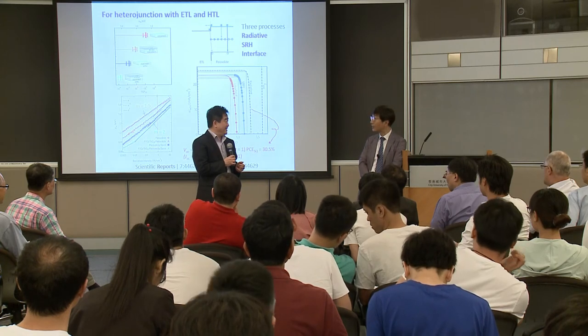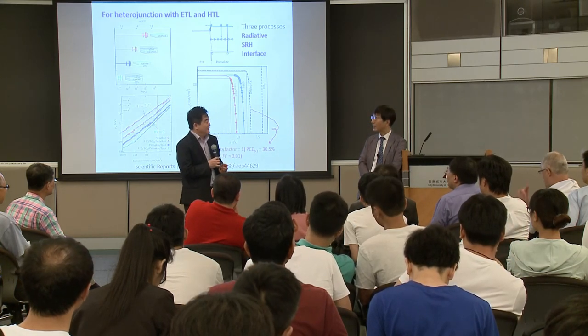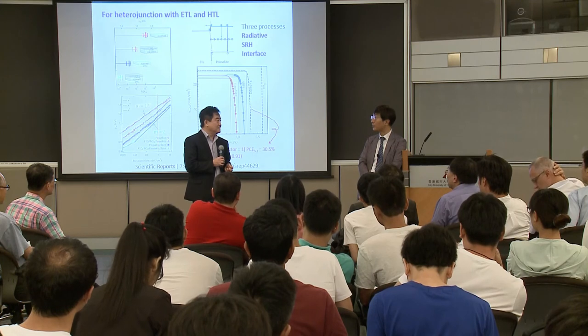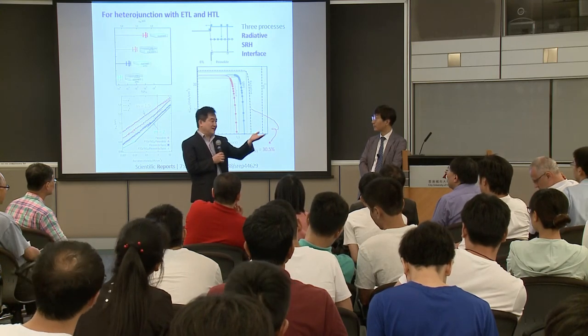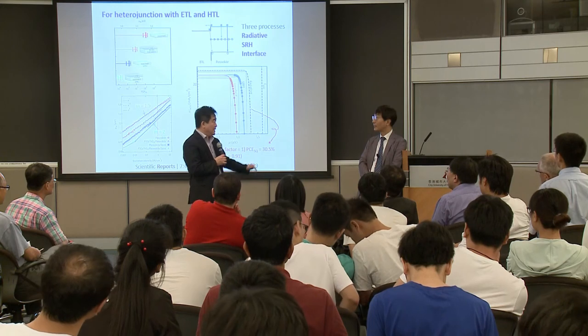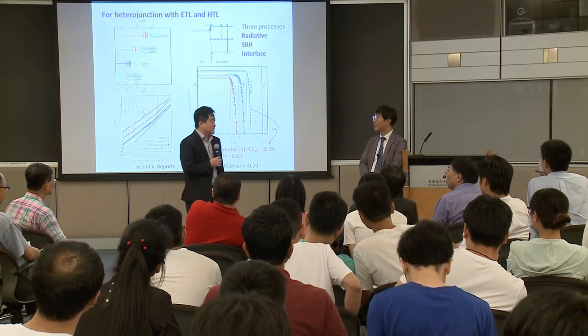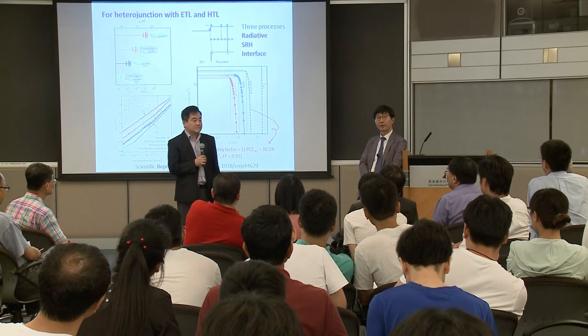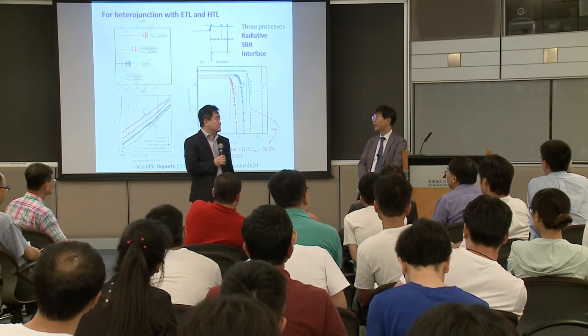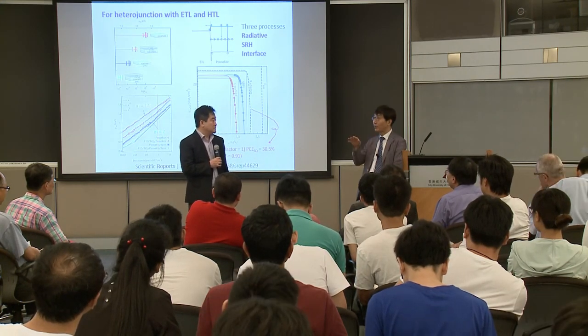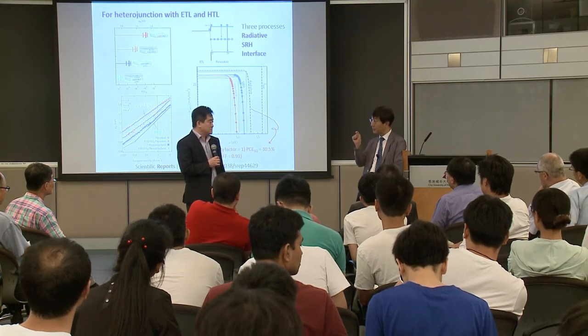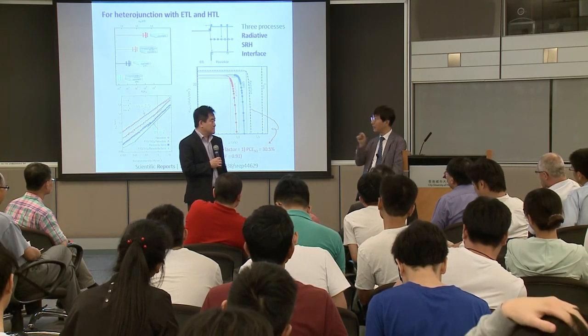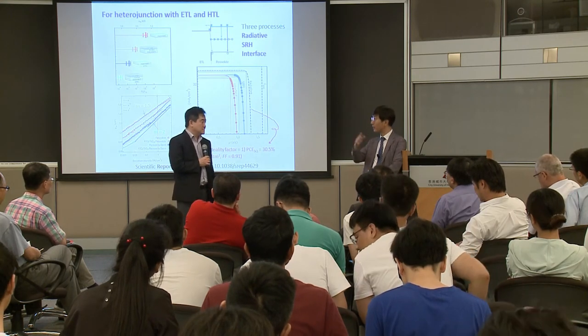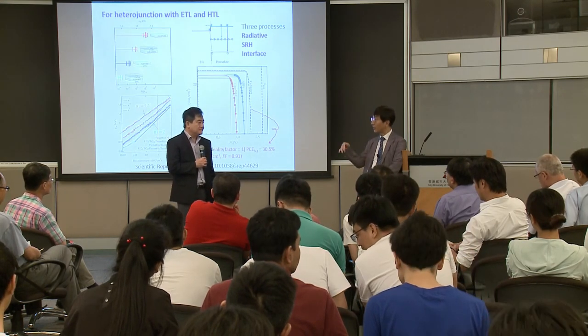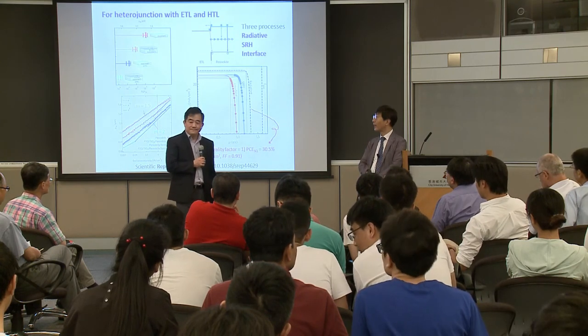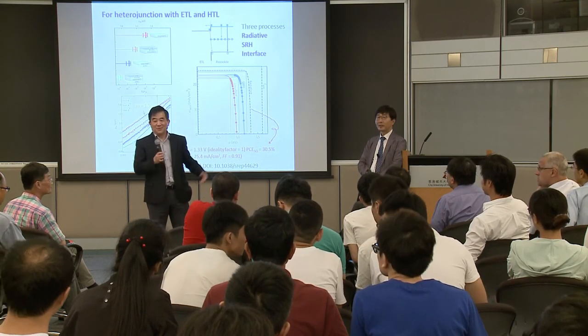Oh, yeah, that is because we decrease the capacitive current a lot. Yeah, because you can have iodide potentially doping the interface of the PCBM. Yes. Really make it conductive. Yes. So this is a kind of, probably I think this is not only the selective contact materials interface, the perovskite interface is probably different from the titanium oxide, the perovskite contacting titanium oxide. Okay. So, any more questions?